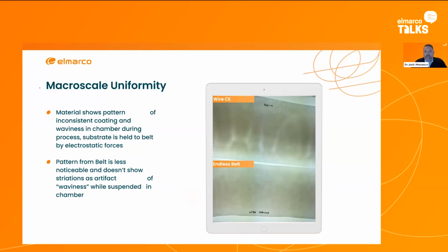And you can see also that electrospinning kind of copies a bit whatever it's coating. So the more uniform the substrate you're coating is, the more uniform the nanofiber layer is going to be. In the case of the belt, you can see it has a very plain pattern. You don't really see a pattern on the material because the belt's very uniform and it collects very well onto the material, and you don't see any sort of impact of the substrate.